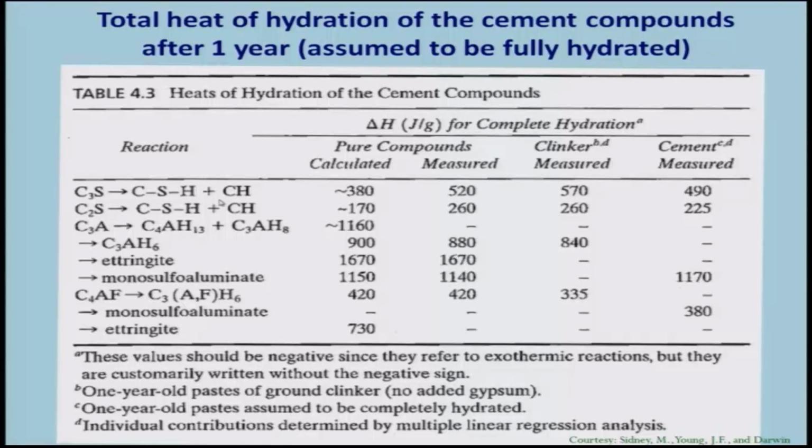Now, for the first reaction, tricalcium silicate, we find that this is approximately 380 joules per gram, and remember that here we have assumed that complete hydration takes place.